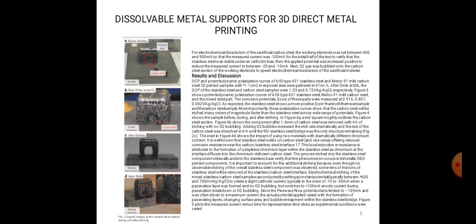Now let's come to results and discussion. OCP and potentiodynamic polarization curves of AISI type 431 stainless steel and Metco 91 mild carbon steel. We selected these metals. The 3D printed sample is shown in figure 2, which shows before etching and after etching in different sections and different views of this sample. Adding O2 bubbles increases the etch rate drastically and results in a highly etched, finished product. Although it is a part that we can use directly, it needs trimming of the surface.